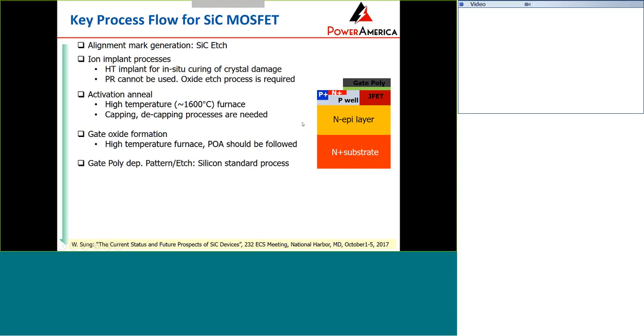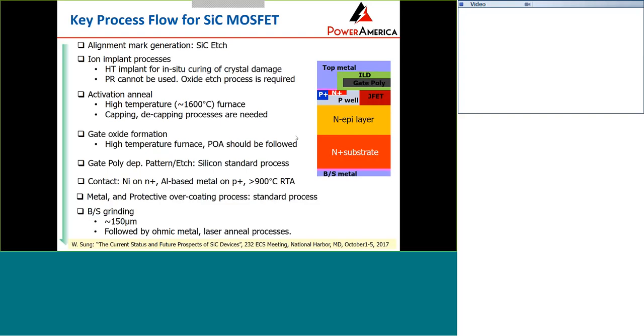After that, we do the gate oxidation, and we anneal this oxide with NO. That's a very well developed process. You do the polysilicon gate, that's the typical silicon process, and make contact. For the contact, you can use nickel for N-type contact and aluminum-based metal for P-type. Some studies have shown that you could use a single metal for both contacts as well. You anneal this contact at 900 degrees or beyond to make it ohmic.